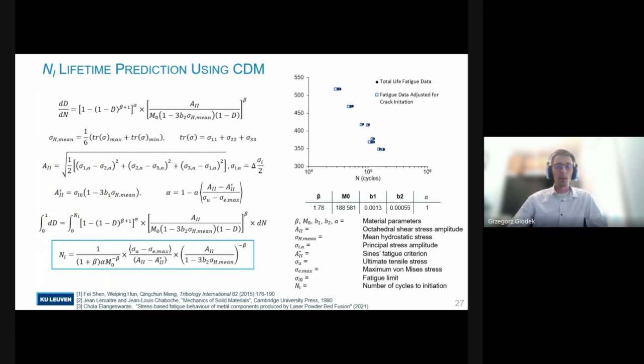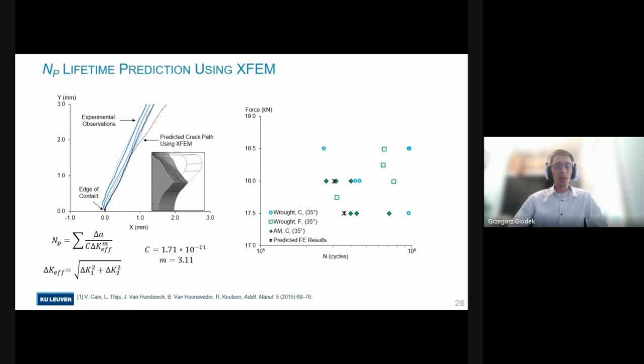Now, also, just a few more words about the finite element simulations, or the modeling campaign that accompanied the experimental results. The continuum damage mechanics model was used to try to estimate the lifetime of the dovetail joint additively manufactured Ti-64 components. This was used specifically for the initiation lifetime, but the propagation path and lifetime were also studied using the XFEM technique. Here we can see that up until 2 millimeters, quite good agreement is reached between the simulated crack propagation path and the experimental observations. But after that, there's some deviation, so there's still some improvement that can be done there.